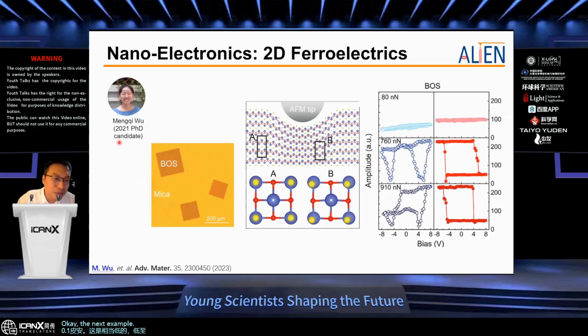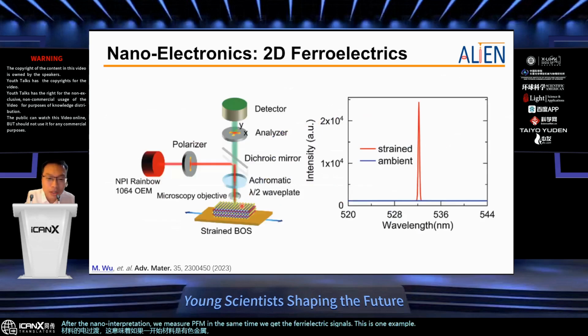Okay, a next example from the first round student is manipulation using the tip to introduce nano indentation of two-dimensional materials. This nano indentation can make the symmetric lattice asymmetric. Then we can create a ferroelectric transition of the materials, which means if the material in the beginning is non-ferroelectric, after the nano indentation, we measure PFM at the same time and we get the ferroelectric signals. This is one example. And it also helps us to understand, at the micro scale, that strain-induced second harmonic generation is also a sign of ferroelectricity.